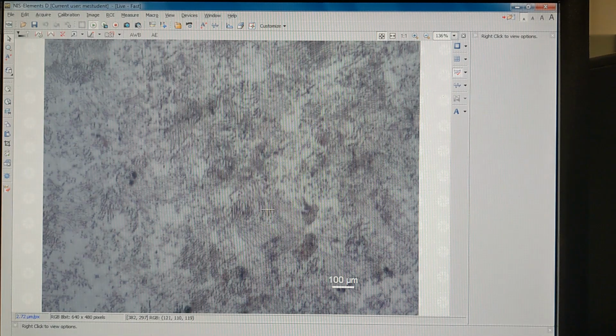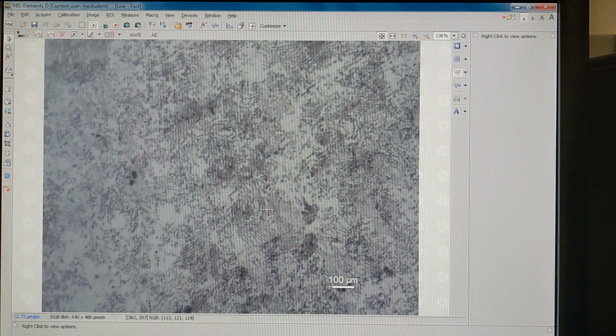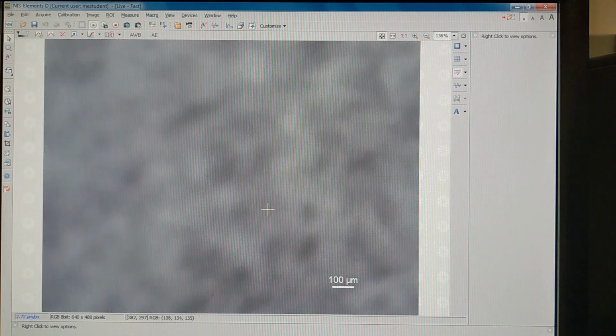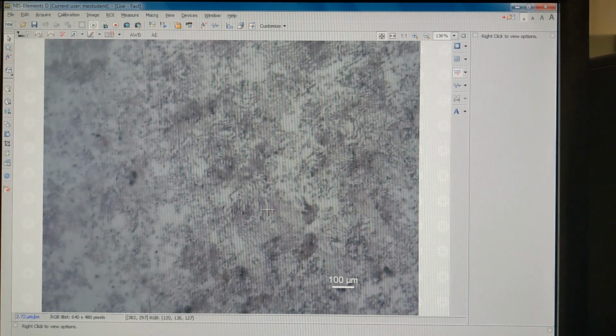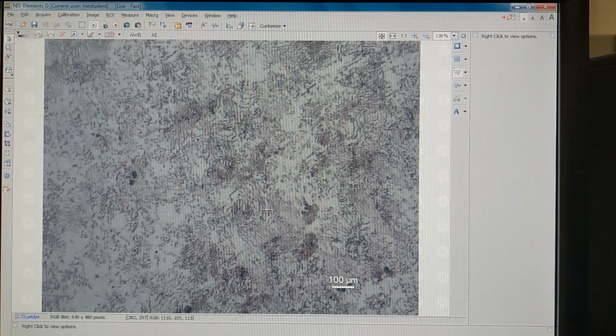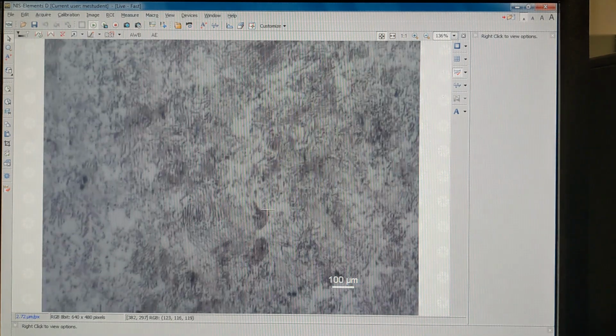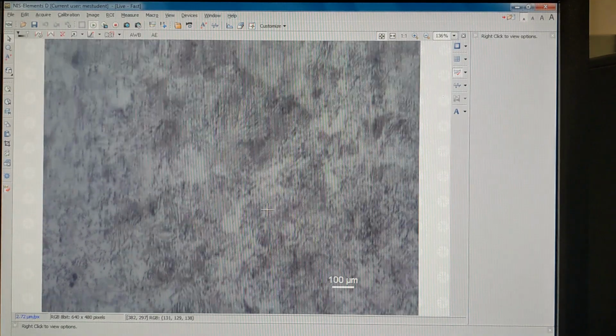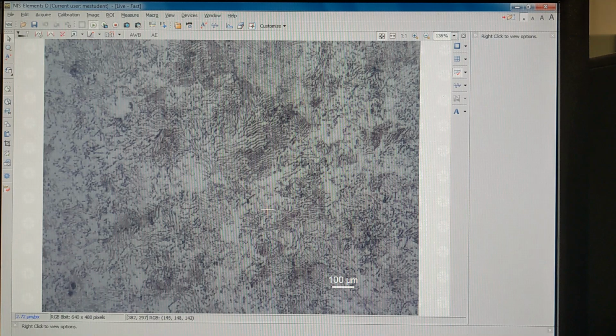So at 50 times, you can start to see our microstructure. 1018 steel has 0.18% carbon, and a big feature of carbon steels is pearlite. Pearlite is a layered structure composed of pure iron ferrite and iron and carbon, a structure known as cementite. It forms layers, which you can actually see if we zoom in. Very, very nice. You see we have these layered structures. The dark regions are cementite, this carbon base, and the light regions are ferrite, the pure iron base.